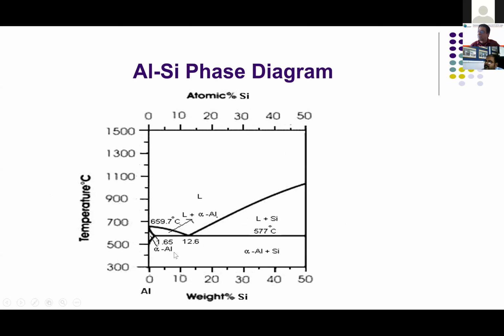Alpha particles of silicon are highly dissolved, rounded or needle-like. Whereas the silicon particle itself will be in the form of flakes or cubes or cuboids, which you can visually see. Sometimes when you break the ingot, the breaking itself will show you a very rough surface. I'm talking about incoming ingots from the alloy supplier. Now that is why I always say the dissolving silicon beyond 12% also is very difficult.